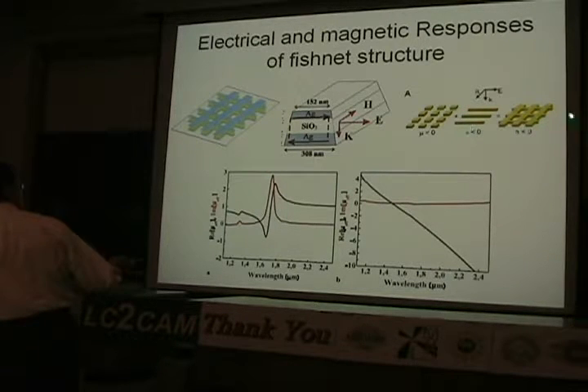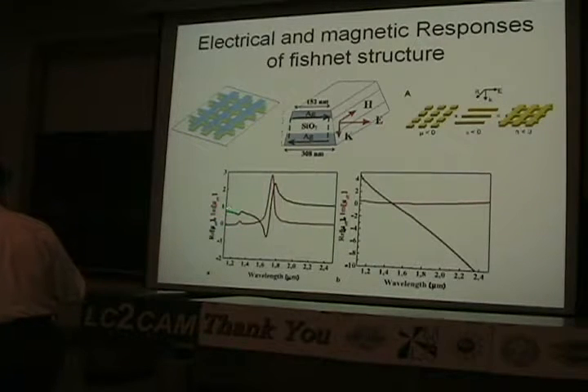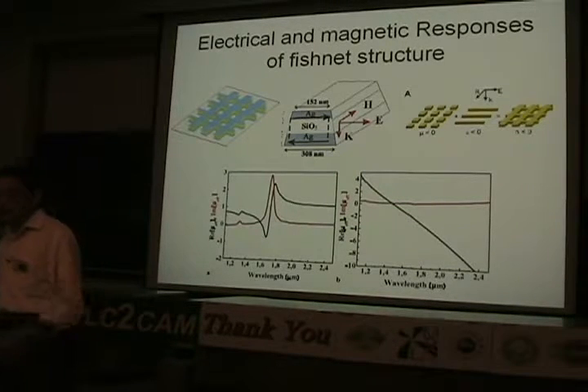So combined together, you have the fishnet, and that gives you the magnetic resonance, the real part like this, and here you have the negative mu. The bars will give you the plasma response, as you can see: below the plasma frequency, you have negative epsilon. And the red curves are the loss curves.